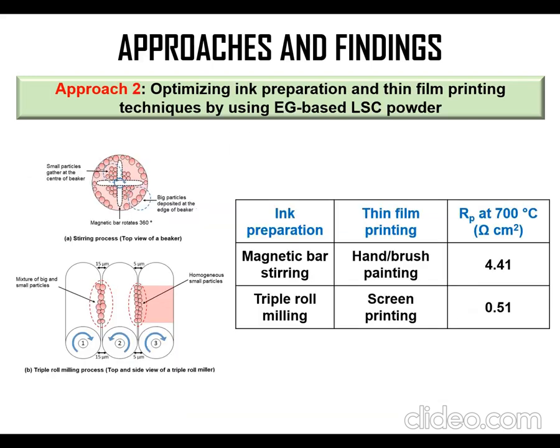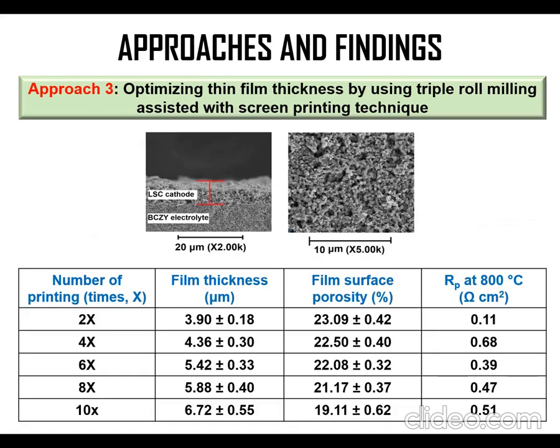Approach number two. We optimize ink preparation and thin film printing technique by using EG-based LSC powder. The lowest RP value was recorded when we prepared the ink using triple roll milling and printed the film using screen printing. Approach number three, we optimize the thickness of the thin film by using triple roll milling assisted with screen printing technique. In this approach, we vary the number of printings from 2 times to 10 times. The lowest RP value was recorded at number of printings equal to 2 times.